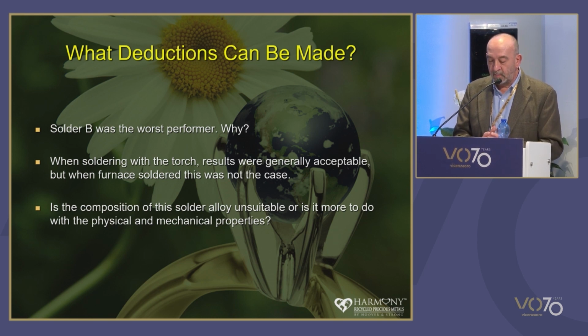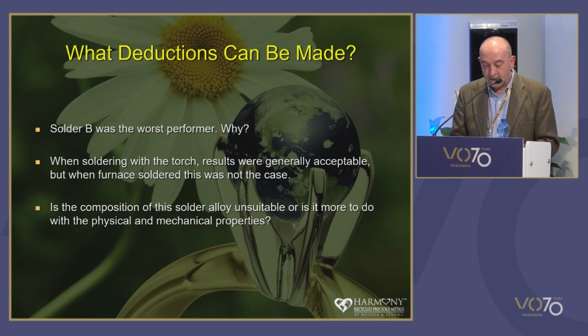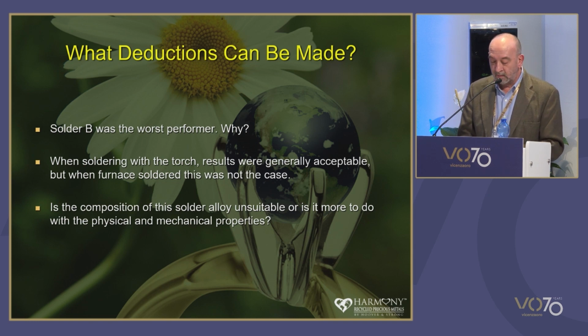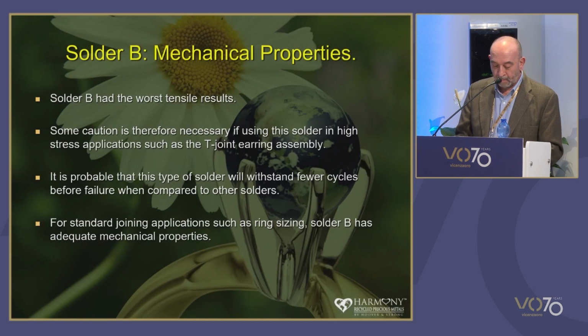Soldering with the torch generally produced acceptable results, but the furnace tests did not. Had poor wetting, poor flow, and the pieces didn't fully melt. If they actually did, the result was lumpy and cratered. So do we consider the composition of this solder unsuitable for joining materials, or is it more to do with physical and mechanical properties? So let's have a quick look.